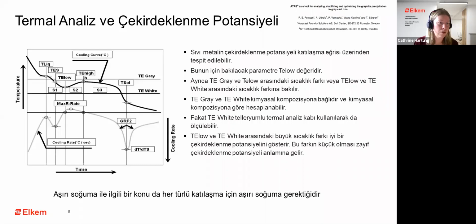The TL, the start of the liquidus, and the TE low is the lowest temperature before nucleation starts of graphite. And then there are different names of the different parts of the curve, depending on which kind of software you're using, but the arrests and the different parts of the curve are the same regardless of which thermal analysis system you're using. It's just the slight difference in where the definitions or where the points are, depending on how the software smooths the curve. But the parameter that is of interest when it comes to nucleation potential is